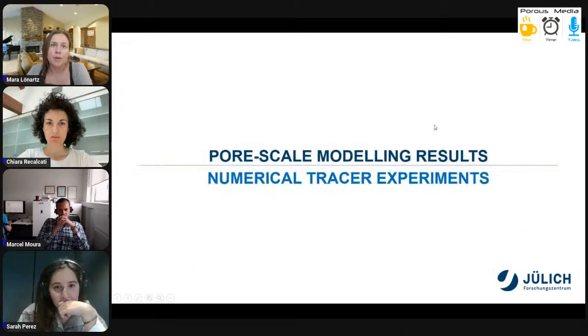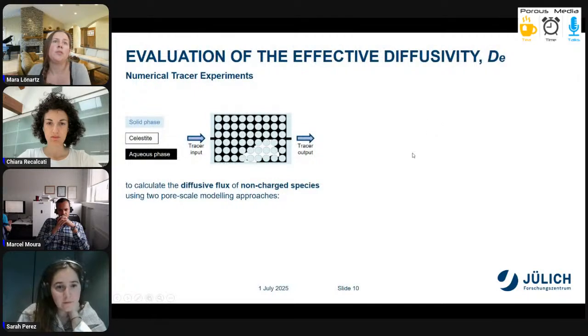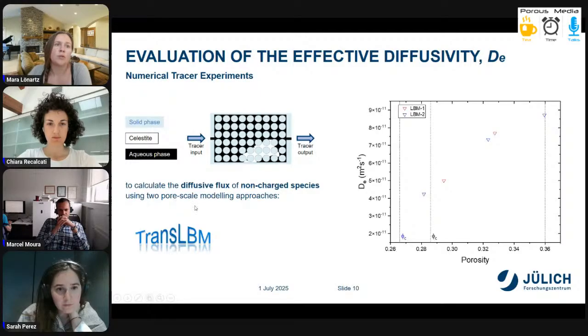So what about the effective diffusivity in response to precipitation? For this, I conducted some pore-scale modeling studies, using the two-dimensional images, which were segmented into three phases: the solid phase, celestine, and the aqueous phase. And then, used as input, the first approach was the so-called Trans-LBM. That was a code provided by Yuan-Kai Yang, my colleague, and it is based on the Lattice-Boltzmann method.